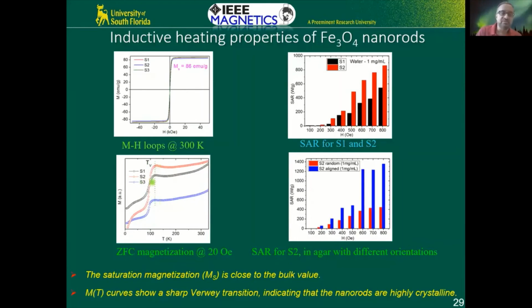You can take it to your low temperature magnetic system and look for the Verwey transition. This is a well-known metal insulator transition in magnetite, Fe3O4. It's one of the largest metal insulator transitions known, and it's a first order phase transition, so you see a change in magnetization. Now here's the transition for these nanorods. Typically in magnetite nanoparticles, you will not see this at all. It's completely washed away. Only in really high quality particles can you see the Verwey transition. So if you make magnetite particles, whether nanoparticles or nanorods, one thing to do is check for the Verwey transition. With that, you can be confident that it's of high quality.